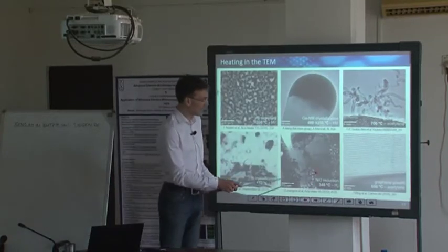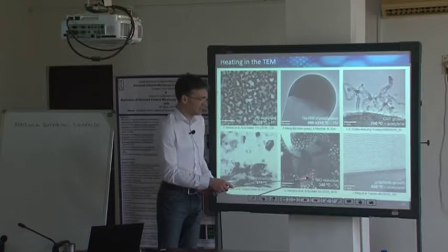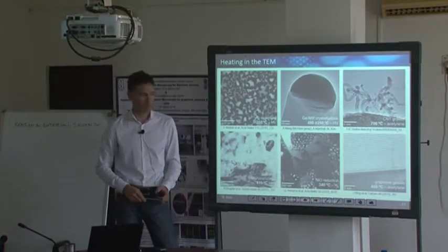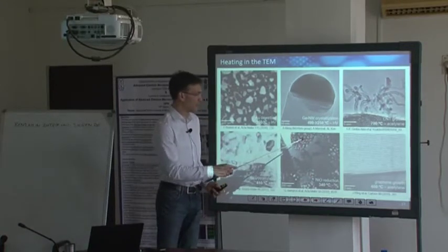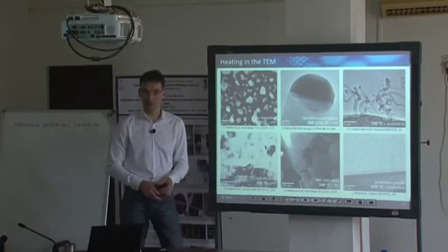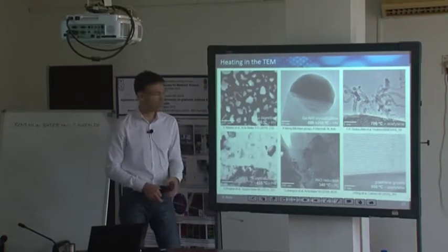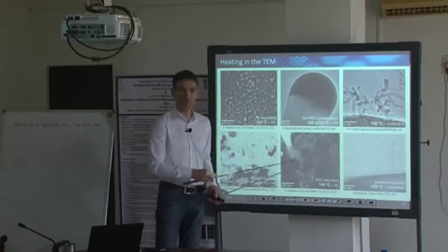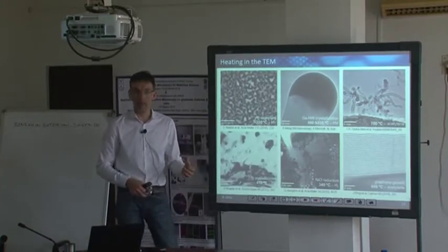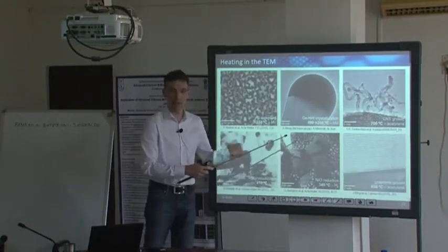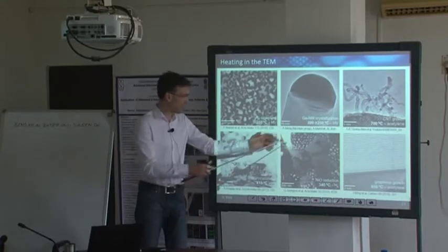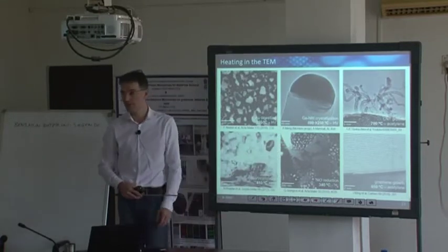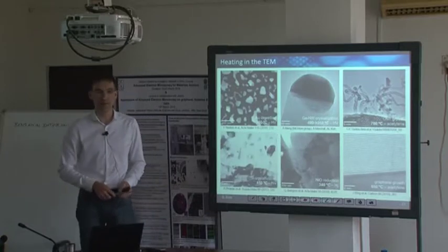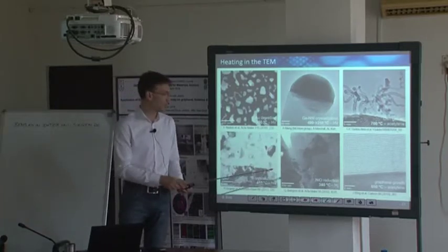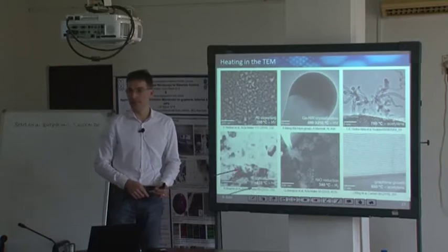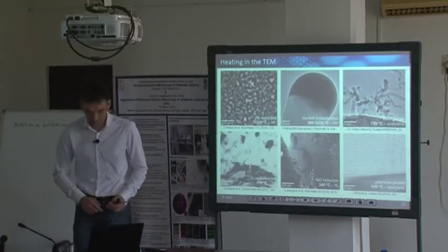If you oxidize that in another step, for instance, it doesn't necessarily mean that all the pores vanish. So just by this oxidation of your nickel, some of these pores might even remain in the material. If pores remain, the volume of one grain is larger than before, and that might cause stresses, for instance. People are highly interested in failure of batteries or fuel cells, so you want to do such, let's say, cycling within the microscope.